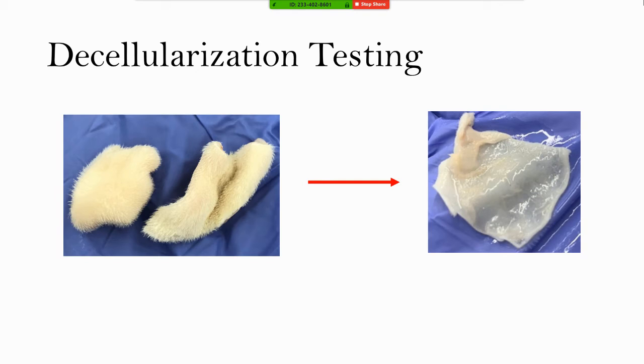The first process of decellularization creates a DECM. On the left is a native skin tissue, and on the right is a decellularized skin. We designed a procedure using trypsin, dispase, and SDS to break open the ECM and wash away the cells and DNA. This leaves behind the structure of skin made up of keratin, fibrinogen, collagen, and elastin.